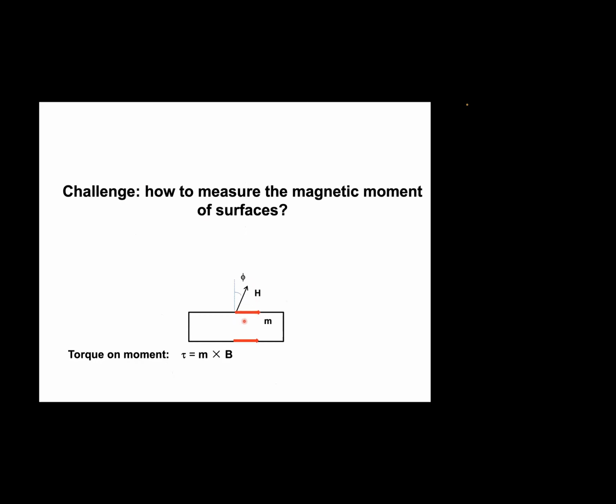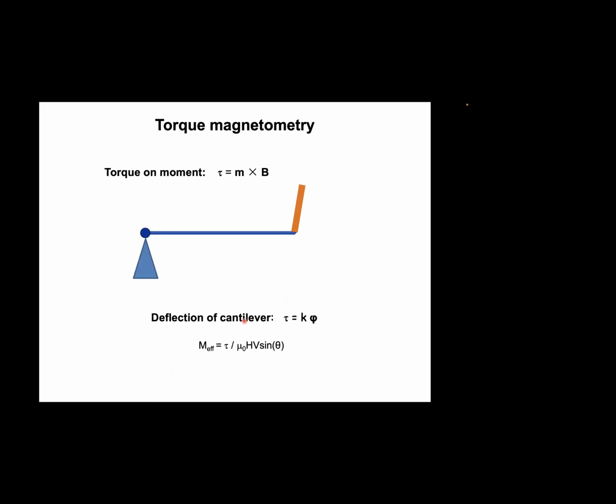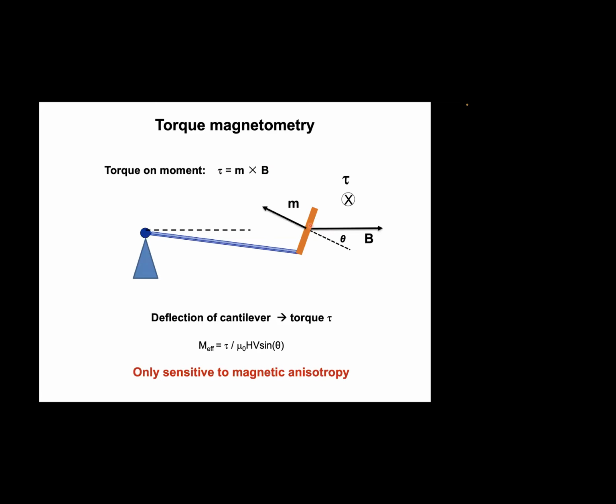So that's a simple principle, and the design is quite straightforward. We have a sample sitting on a floppy cantilever. Apply a magnetic field. If there's an anisotropic response, that means we're going to generate a torque, and that torque would deflect the cantilever, and from that we can calibrate and know the torque and the effect of magnetization. Let me also emphasize that I'm measuring a torque, M cross B. That means I have to have an anisotropic response. If it's completely isotropic, nothing will happen, right? So that turns out to be a way to really select the response that gets emphasized by the elongated Fermi surfaces.